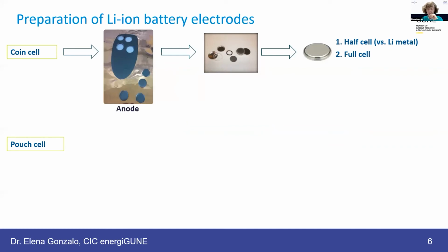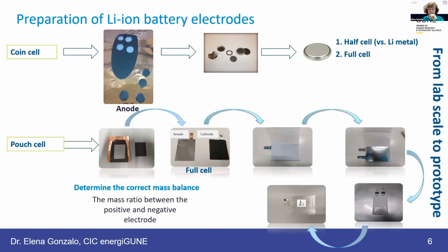One was the coin cell configuration. We had to cut the anode in round shape to be assembled in coin cells. And we were testing half cells versus lithium metal or full cells versus the positive electrode. The second device we were assembling was a pouch cell. We were following more or less the same steps. We were cutting the electrodes, we were selecting the cathode material, and we had to determine the correct mass balance, that is the correct mass ratio between the positive and the negative electrode in order for the cell to work properly. We were assembling the cell and using the separator in order not to have a short circuit, doing the pre-cycle, degassing the cell, and finally we got this pouch cell.